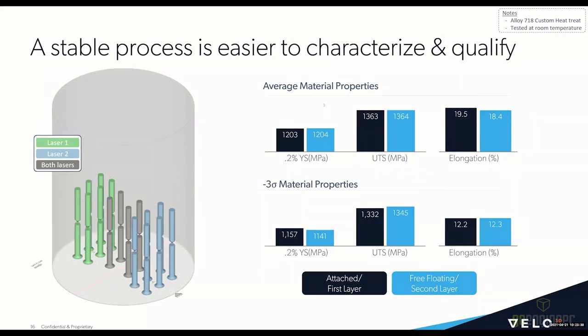So basically what we're doing with the plots here is we're verifying, you can see here on the left side of the screen, a layer of attached bars to the build plate, a layer of free-floating bars above that, and then also laser one, laser two, and dual laser bars. Dark blue is the attached and first layer. The light blue is the free-floating or the second layer. And you can see consistency both in the average and the minus three sigma properties between these two different data sets.